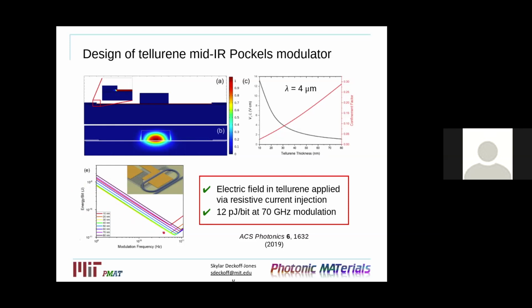But we see, interestingly, that at intermediate thicknesses of around 40 nanometers to 30 nanometers, we see optimal performance at very low energies of 12 picojoules per bit and modulation speeds of 70 gigahertz. And again, this is for a particular architecture using a ring resonator, but by going to Mach-Zehnders, we can go to higher frequencies at the expense of the energy per bit.